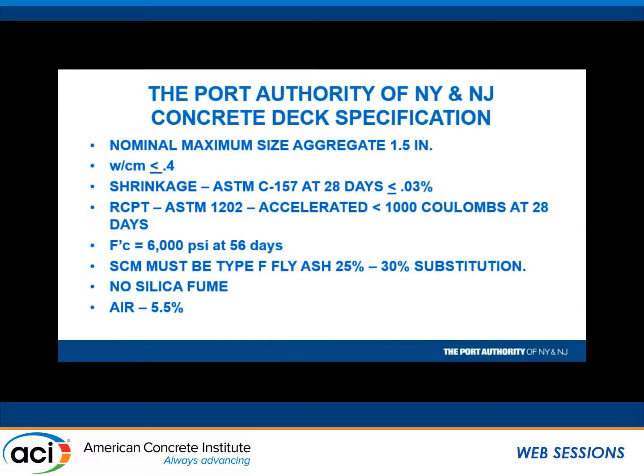The other thing that we did, again, Colin Lovell said we shouldn't do this, but we did. You must use type F fly ash, okay? Now, why? We didn't do this just to be arbitrary. We found through the years that for bridge decks, structural decks, we get less cracking when we blend fly ash with cement. The most cracking we got is when we use silica fume. It was horrendous in general. Bad, not good, terrible finishing, terrible cracking. Then we went to slag. Slag produced some cracking, not as much as silica fume. We found we got the best results with fly ash.